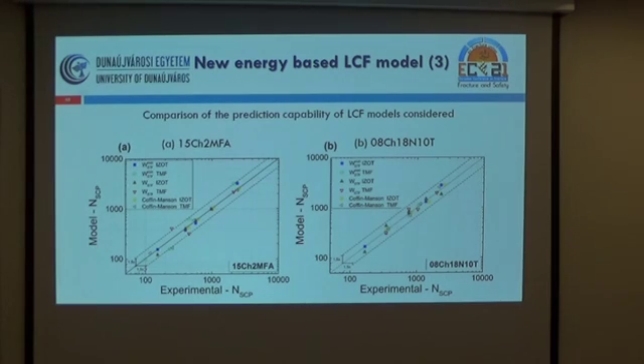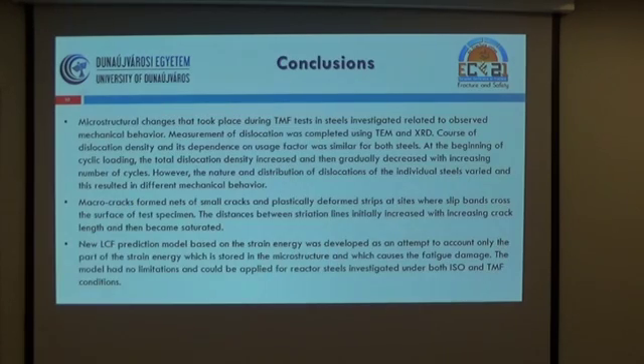We tried to compare the prediction capability of the low cycle models which we considered, and then we put here the well-known Coffin-Manson models, for which I did not show the results, but of course we evaluated the results based on this too, and also the energy-based models. And you can see in both materials investigated a quite well correlation between the total strain amplitude versus cycles and the energy-based criteria.